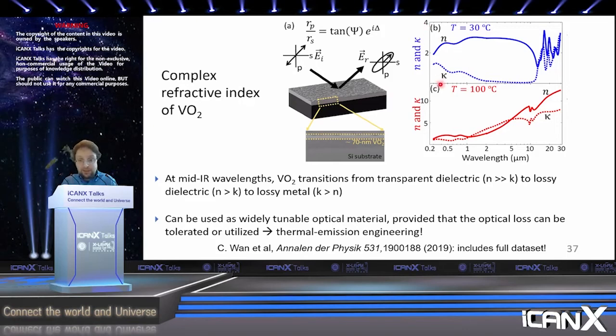So this is the complex refractive index below the phase transition temperature and above the phase transition temperature, all the way from the UV to the far infrared, for wavelengths from 0.2 microns to about 30 microns. This is done with a pair of spectroscopic ellipsometers. And you can see a few interesting features. One is that, of course, you have this enormous change in the optical properties. In other words, in the mid-infrared, VO2 transitions from being a transparent dielectric, more or less, to being a lossy dielectric, to being a lossy metal.